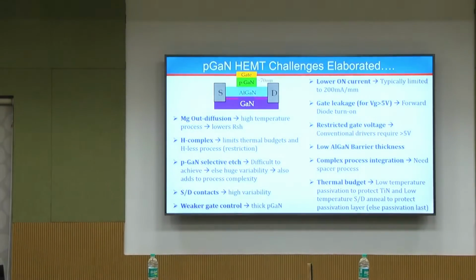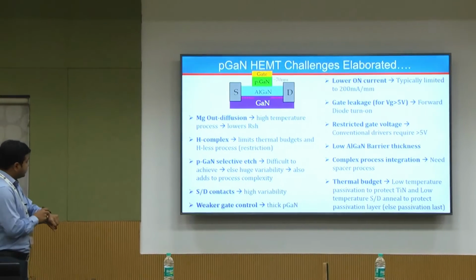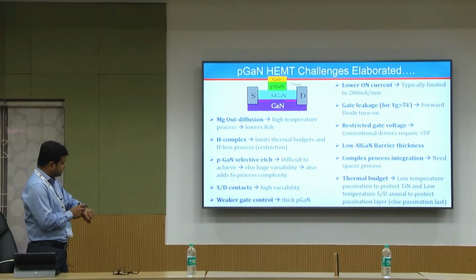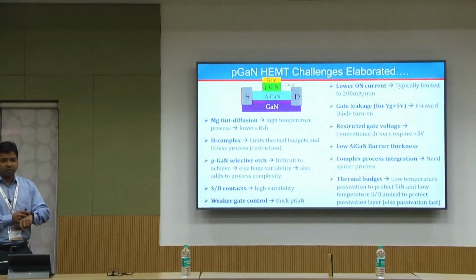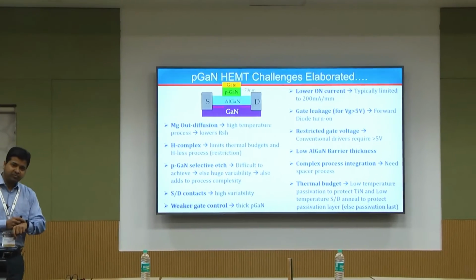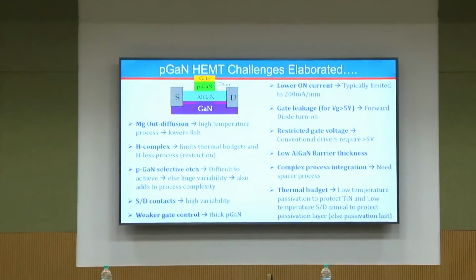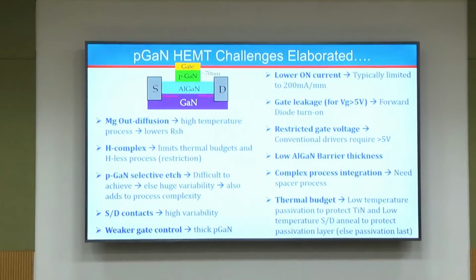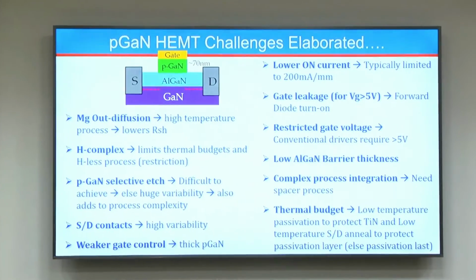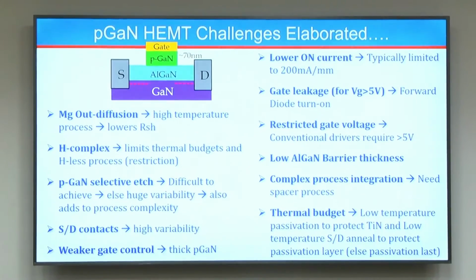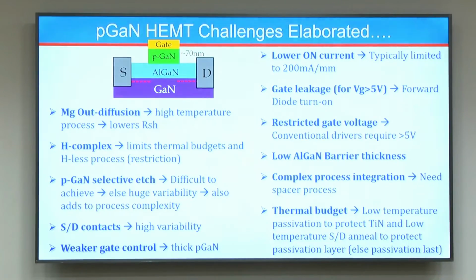Okay, so let me elaborate on some of these points that I said. So magnesium out-diffusion, so what happens is the pGaN is doped p-type by magnesium. Now this magnesium can diffuse out at a certain high temperature. So if you are running high temperature processes, then you will have possible magnesium out-diffusion into the barrier layer, the AlGaN layer, and then that is going to further deplete the 2DEG. Which is something you have to avoid, right?